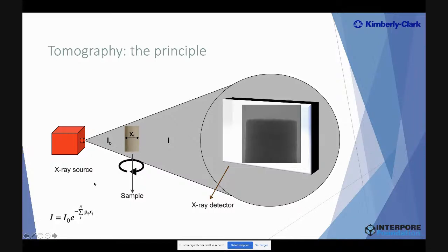And this is explained in the law of Lambert-Beer, where you see also the impact of mu, which is the linear attenuation coefficient, which depends on the average density of your material and the average atomic number of your material, as well as x, which is in this case the path length through which the X-rays have to penetrate your sample. So the thicker your material is and the higher your average linear attenuation coefficient, the lower the intensity of your X-ray source coming out will be. So that is very important.